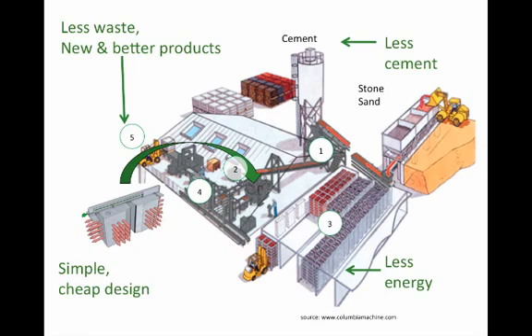It can be between 4 to 12 products at a time, and that's every 10 seconds all day long. When they first leave the block machine, they're strong enough to stand up under their own weight but are still very fragile. Those are sent by conveyor belt or cart to a curing chamber, and it's in the curing chamber that they develop the required strength to be sent out to inventory. Curing takes about 8 hours or overnight, and it's highly energy intensive as steam is introduced into the curing chamber to strengthen the products.